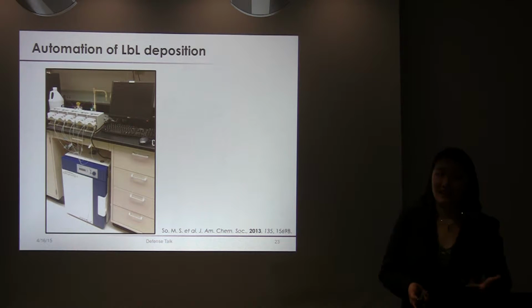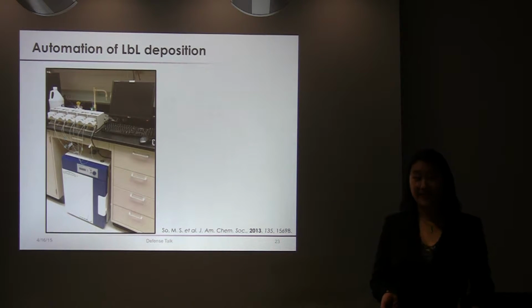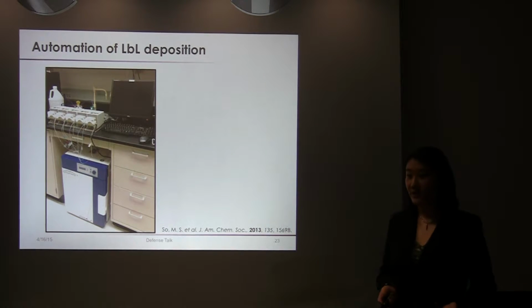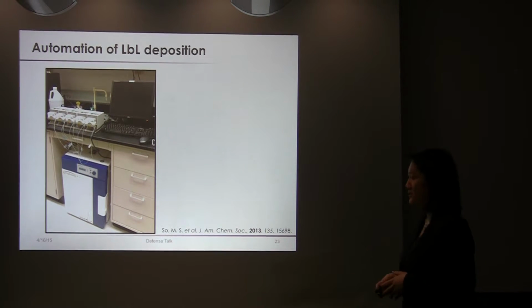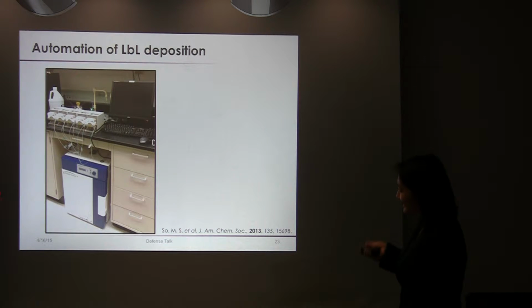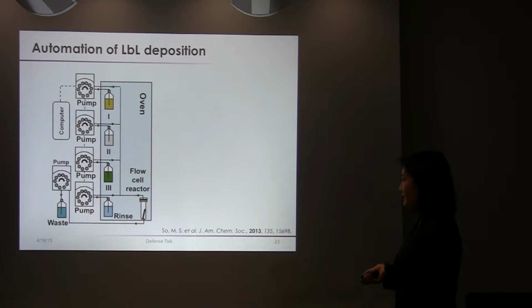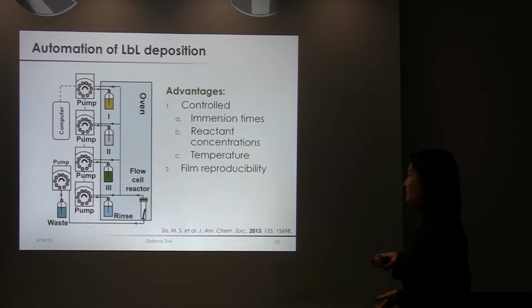So you can imagine that if I actually did this manually, it would take a very long time. So what I did to improve the efficiency of this process was to build a robot that Joe had mentioned earlier. And this is what it actually looks like in the lab. Schematically, if you break it down, this looks kind of complicated, but what I really need you to know is that the system allows for very good control of the immersion times of the pre-functionalized substrates. The reactant concentrations are very well controlled, as well as the temperature of the system is very precisely controlled. And because this is an automated technique, you get very good film reproducibility.